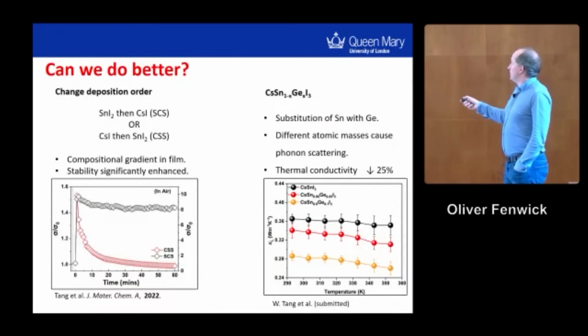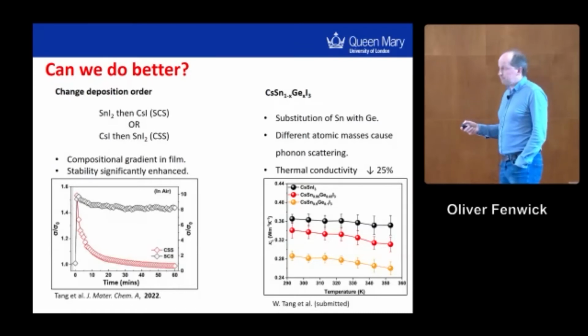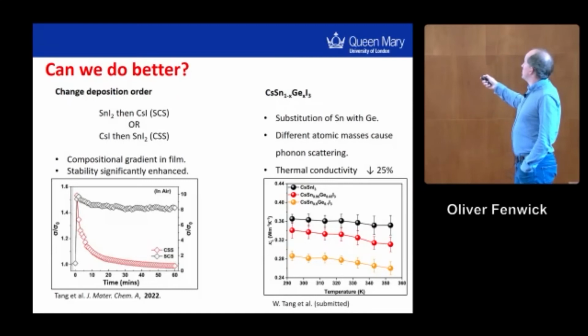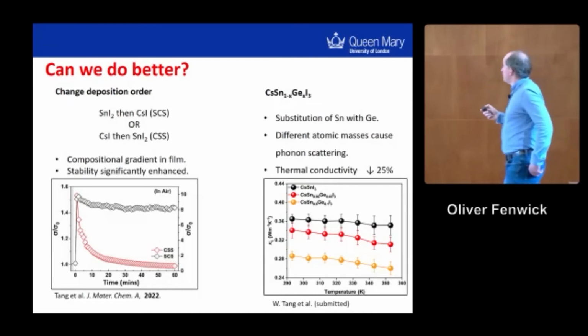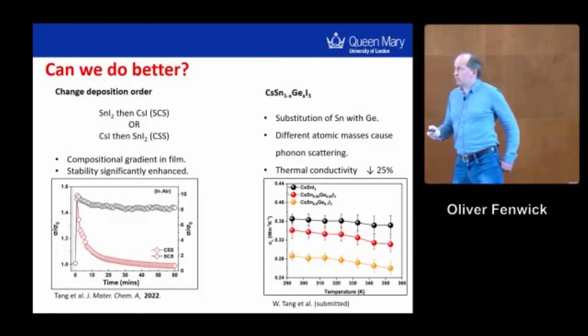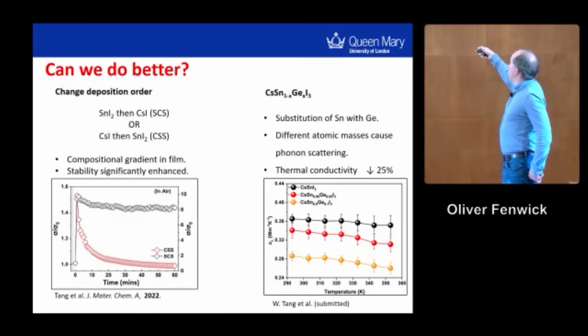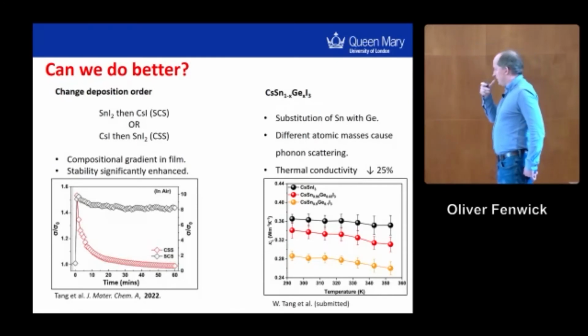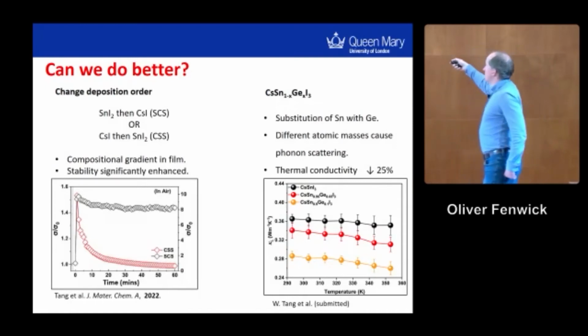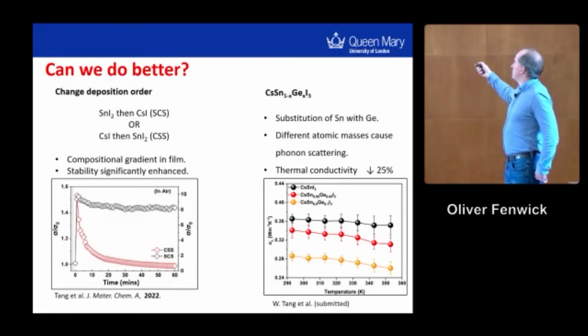We're continuing this, we're looking at stability studies, so one is to change the deposition order between cesium iodide and tin iodide. It turns out that has a huge effect on the stability. And another is to substitute some of the tin with germanium, and that has a different mass, different bonding, and what you then hope is that gives you some phonon scattering. And it does, it brings down the thermal conductivity by another 25% to slightly less than 0.3 watts per meter Kelvin. And so we're still working on that.